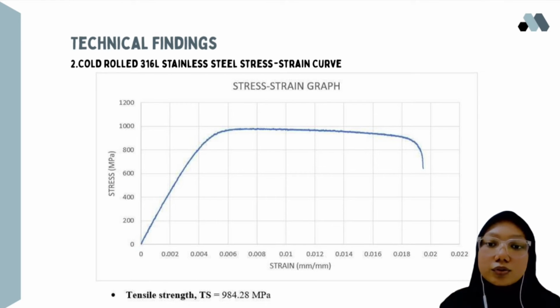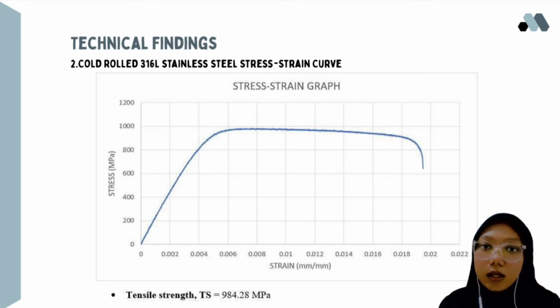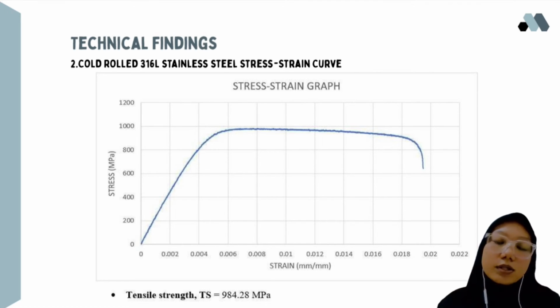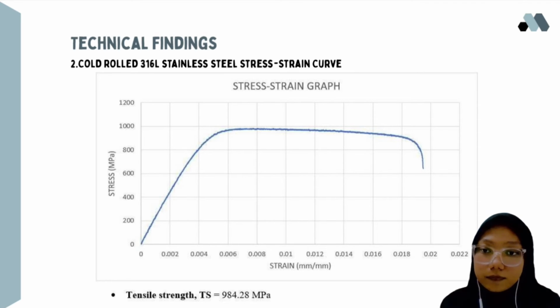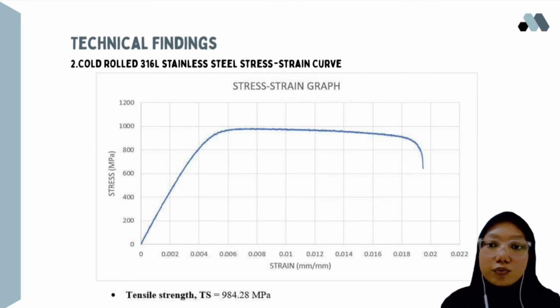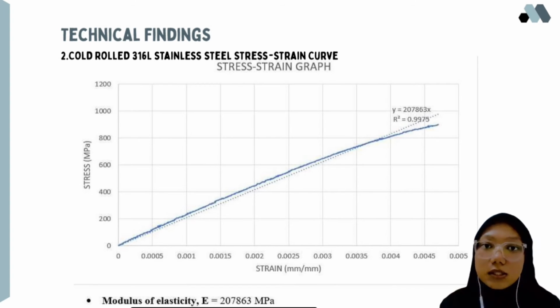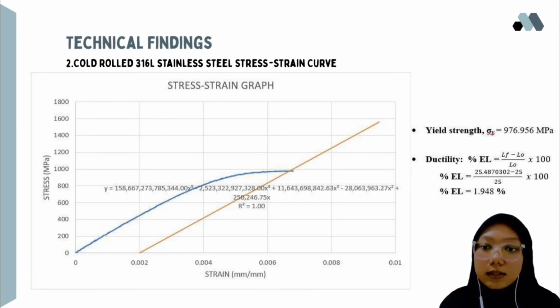22.129%. Next, for the cold-rolled 316L stainless steel 1.0 mm stress strain curve, the curve is constructed up to its maximum load of 8.025 kN. From the curve, by determining the maximum stress, the tensile strength obtained is 984.28 megapascal, while the modulus of elasticity is 207,863 megapascal. By using the same method as for original 316L stainless steel, the yield strength obtained from this curve is 976.956 megapascal, and the ductility percentage calculated is 1.948%.